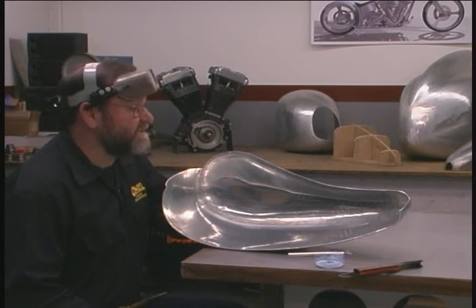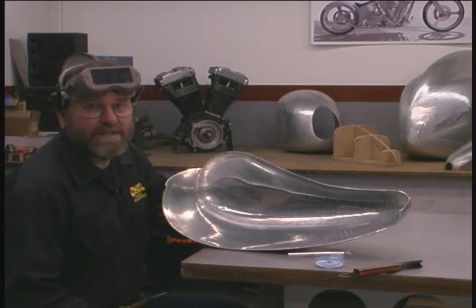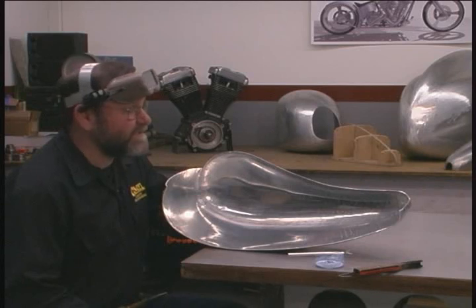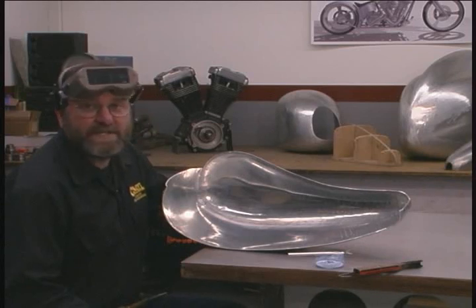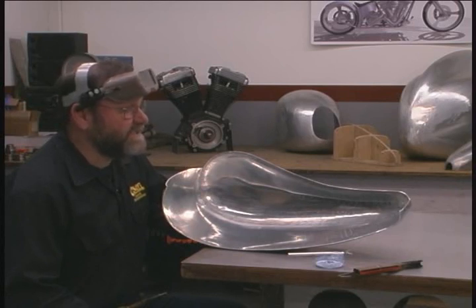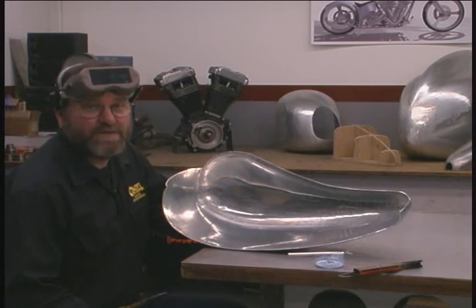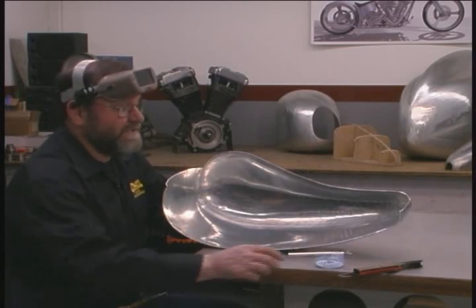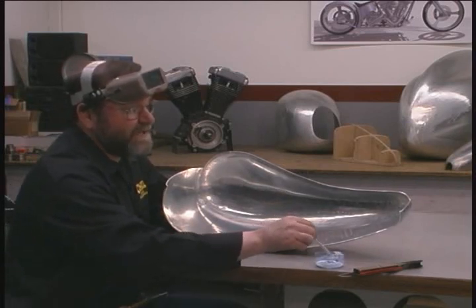Another advantage is that the weld you get from oxyacetylene welding is very soft, and this has some great advantages. One is that it's easier to hammer the weld flat after it's in place. Another advantage is that the soft weld is less prone to cracking than a TIG weld, which tends to be harder. So it takes a few special things to make an oxyacetylene weld.